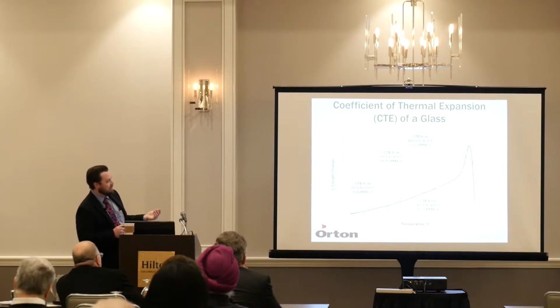It would not be really beneficial to say that the CTE up to 438 is 19.56, because not at one point along there do you actually have that CTE. Additionally, you have a CTE from 400 to 438 of 993.62 parts per million. That's really high. That's not an actual CTE that would be valuable for this process, because typically, based upon where you're going to be working with the glass, you're not going to be seeing expansions like that for a very long time.